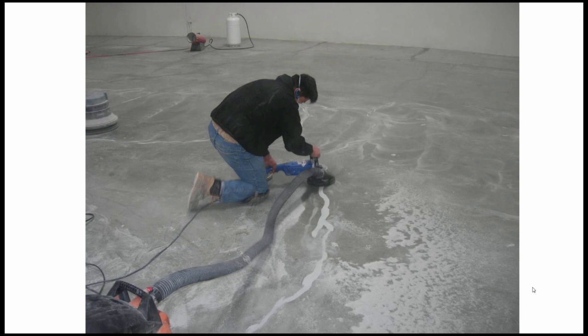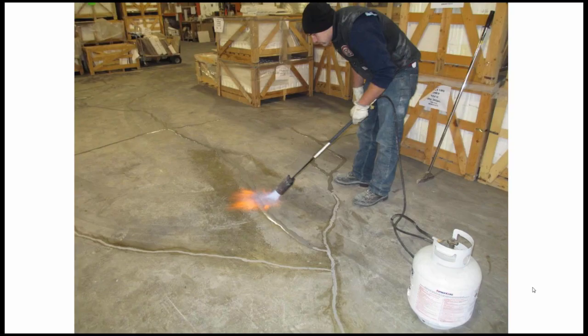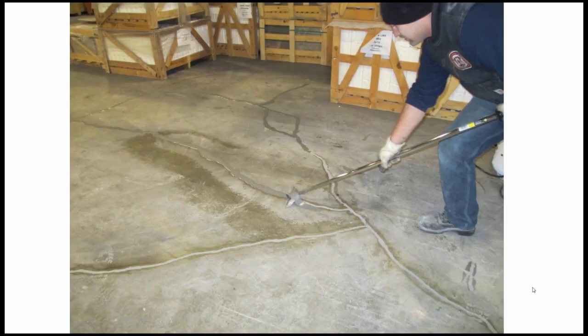And this is an example of the guy shaving it off. Really nice clean surface when he's done, you can see there. And again, in addition to grinding the top of the surface off, if you use the epoxy, this doesn't work with the polyurea, but if you use the epoxy, you can heat the overfilled material up, kind of warm or basically hot without melting it, with a torch. And then if you use a really sharp razor blade, you can slice it off really nice and clean with the surface. So this is a nice method.